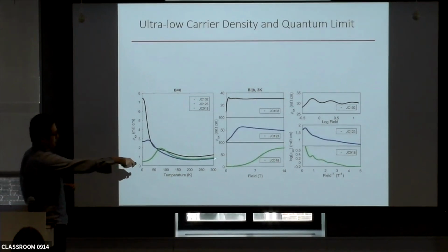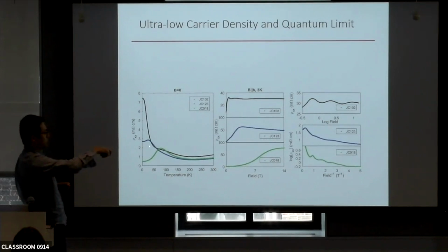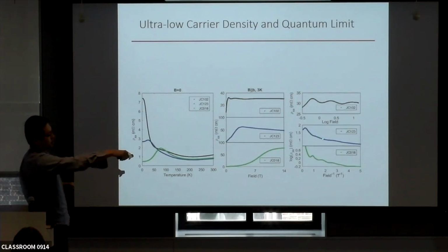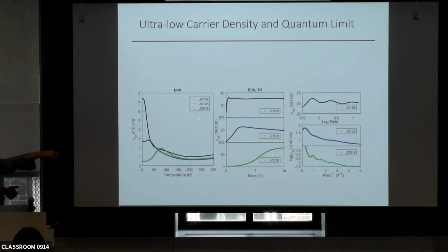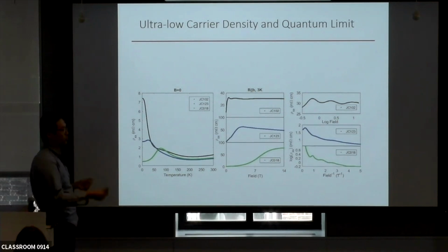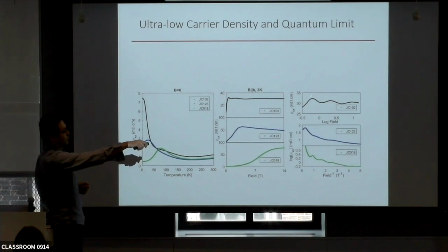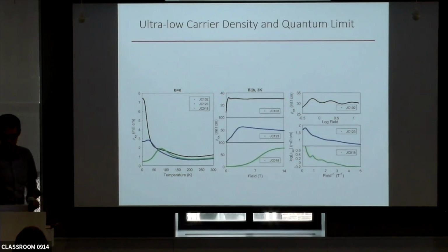For example, for these green crystals, you can see quantum oscillations in 1/B with a periodicity of about 1 Tesla. For the blue crystals, where you push the resistance peak down to 20 Kelvin, the quantum oscillation frequency is about 0.5 Tesla. For this black crystal, you're no longer seeing quantum oscillation. You probably reach the quantum limit as low as 0.1 Tesla, and then you begin to see some very weird log B oscillations in the ultra quantum limit. This is something very interesting, but I won't discuss it more in this talk.